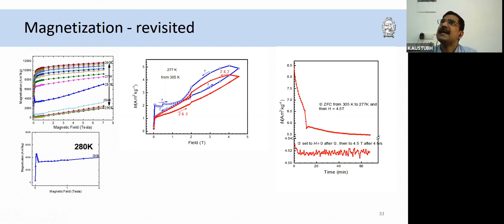But the temperature was maintained the same, 277 Kelvin. And then after about 4 hours, we reapplied the 4.5 Tesla magnetic field, and we see that now the magnetization is almost constant. It does not have this kind of initial fluctuation. So that sort of explained why only in the first cycle we got this reversal behavior, but not in the following cycles. And it also explained that the relaxation time is of the order of a few minutes at least, so that you can complete the one cycle fully.